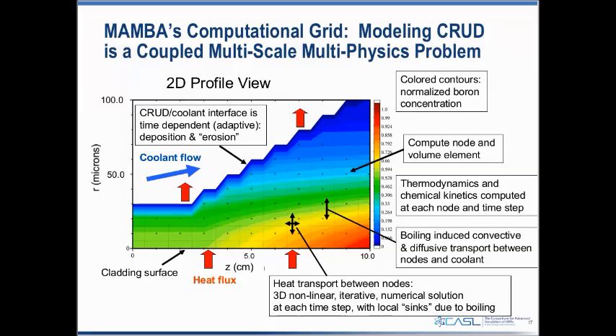We can determine where the temperature is greater than the saturation temperature and the regions where boiling is occurring within the CRUD layer. This boiling induces flow through the porous CRUD, and it draws in soluble boric acid, lithium hydroxide, as well as the nickel and iron that are also in the coolant. These species get concentrated near the cladding surface, and if they reach a high enough concentration and the temperature is high enough, they can then precipitate out of solution and form a solid phase.